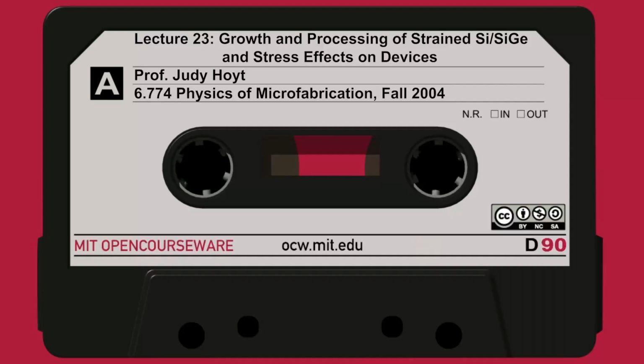So, but let me just mention here on slide 7, this is the IBM work in 1997. In STI, we learned in this course, you fill up the shallow trench with, well, first you oxidize the liner, then you fill it up with LTO, or some low temperature oxide. What they did was grow an oxide liner for isolation, and then they filled the trench with polysilicon, which they thought would induce a lot of compressive stress, pushing in all around the edges of the device.